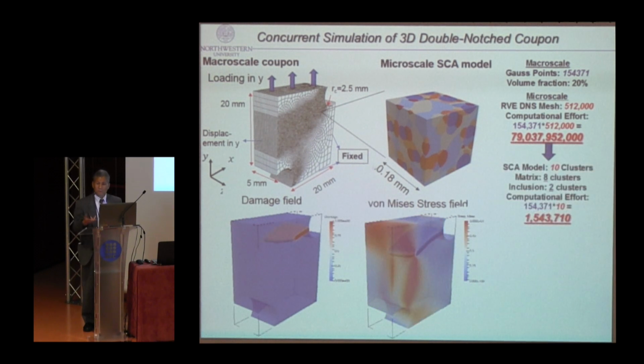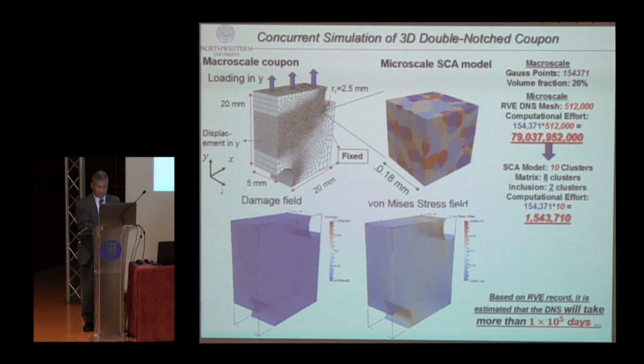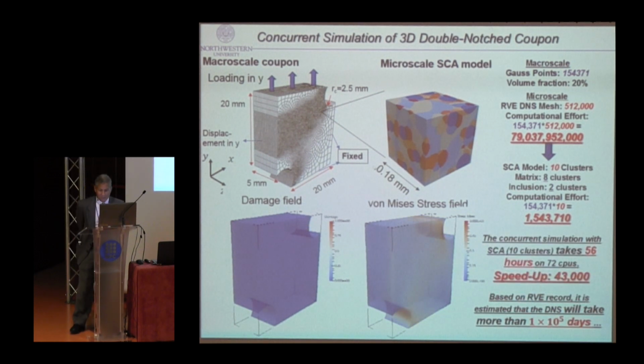I'm going to do data compression. I only use 10 clusters, and that is my computational cost. And based on this RVE calculation, if you compute everything like this, it takes about 10 to the 5 days to do the calculations. And I can do this in 56 hours on the 72 CPU. The speedup is about 43,000 in this case.